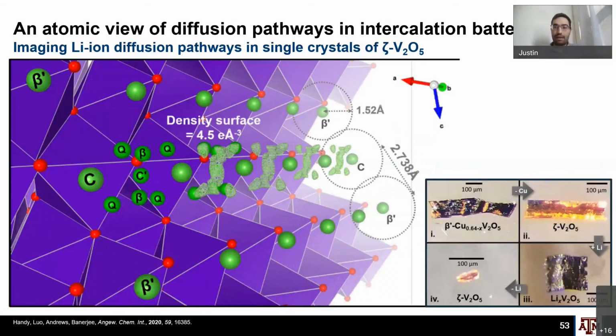And then going beyond that, recent work that was primarily done by Joseph Handy, we're actually able to make single crystals of these metastable materials as well. So these are single crystals of zeta V2O5. They're nice and yellow, just like alpha V2O5. What we can do is topochemically lithiate these and look, using single crystal X-ray diffraction, at where the lithium sits within these materials, and actually image these diffusion pathways.